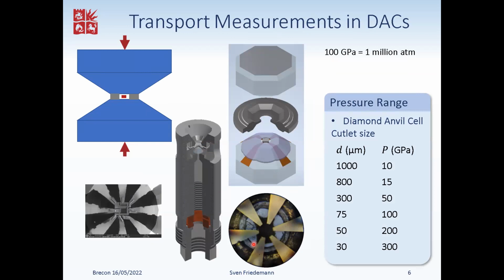It becomes too low in intensity and too broad above 50 GPa. From 50 GPa onwards, what we use is the diamond itself. The diamond has a vibron, which is visible in Raman. I've got some data later where I'll point this out, and it does shift as a function of pressure. As the pressure is increased, the diamond lattice becomes more stiff and the vibron goes to higher energies. By detecting the Raman signal of this, focusing on the diamond very close to the sample, so essentially at the culet, we can detect the pressure at the sample.